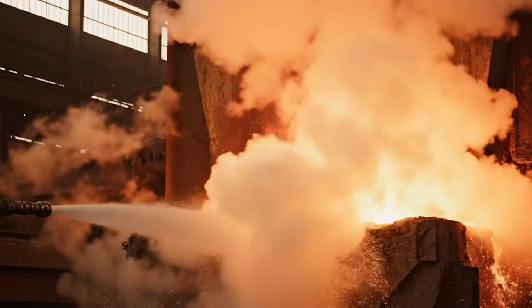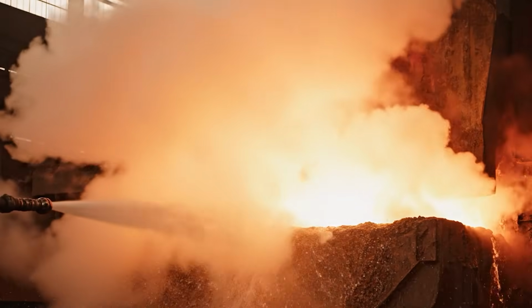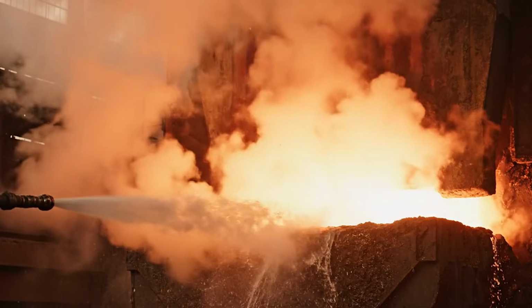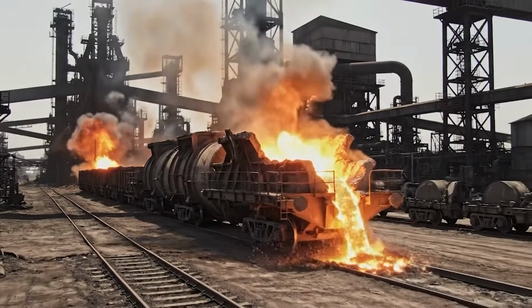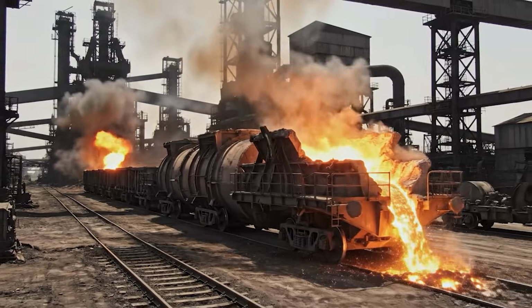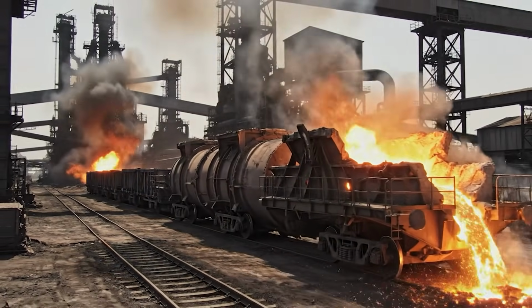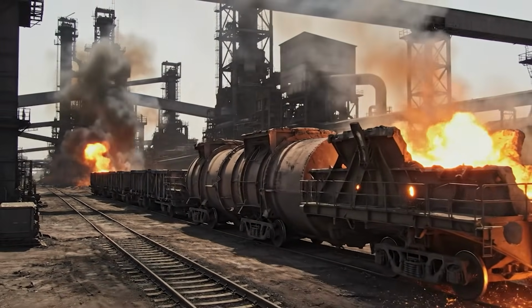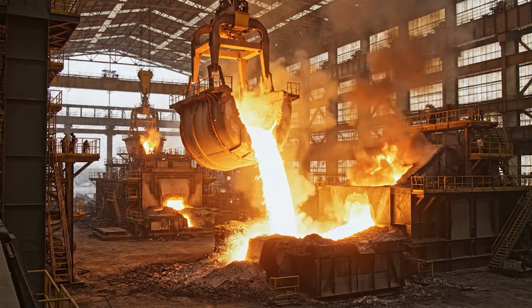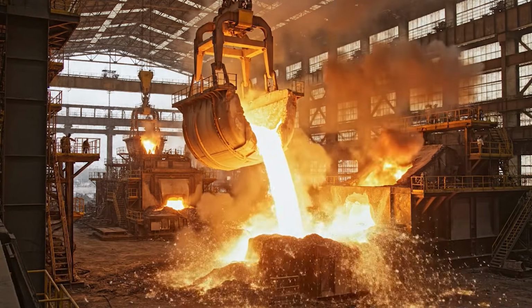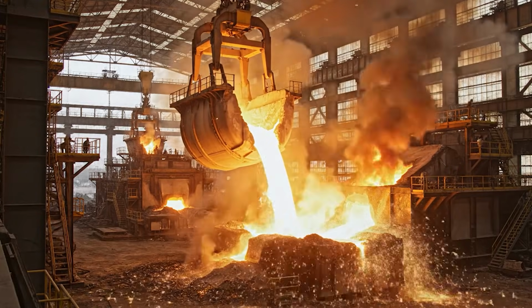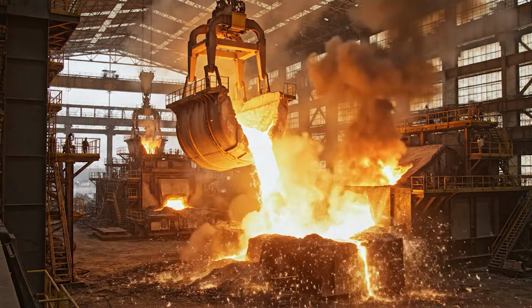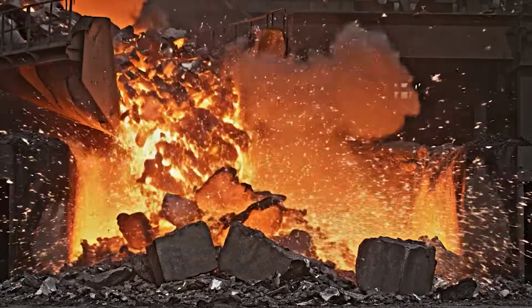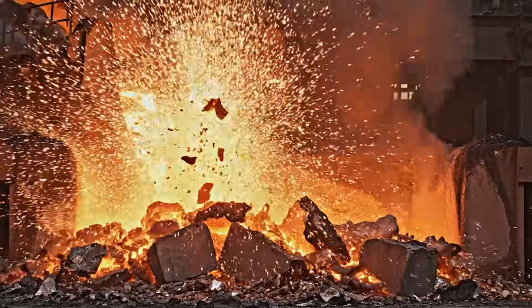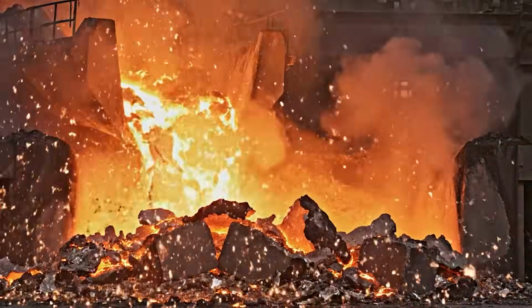Hot metal alone is not steel. It still contains too much carbon, so it is transferred immediately to the basic oxygen furnace. A lance injects pure oxygen at extreme speed. The reaction is violent. Carbon burns off in minutes. Silicon, manganese, and phosphorus are removed. Chemical composition is adjusted precisely for wire rod grades. Each heat lasts only a short time, but the sequence never stops. Molten steel flows out, wiped clean, controlled, and ready for shaping.